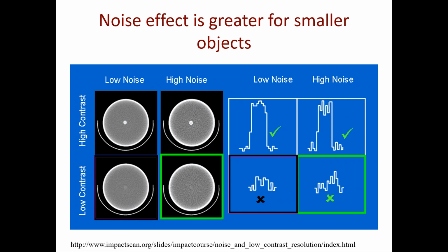So the difference between CT values across smaller objects would be smaller than for larger objects, even though you have the same material in the small object. Let's say that you have an emulsion with small bubbles and large bubbles. Those bubbles are the same phase, and the surrounding is the same phase. But when you image them, you will have a smaller jump across smaller bubbles than across larger bubbles. Same thing goes for thinner fractures versus thicker fractures.